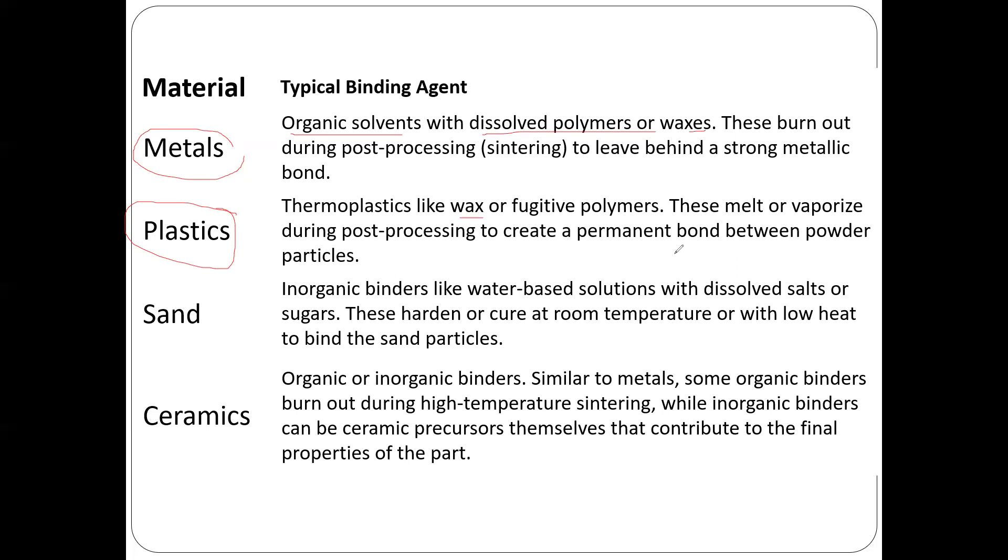If I'm dealing with sand-based materials, inorganic binders like water-based solutions with dissolved salt or sugar are used. These harden or cure at room temperature or with low heat to bind the sand particles.